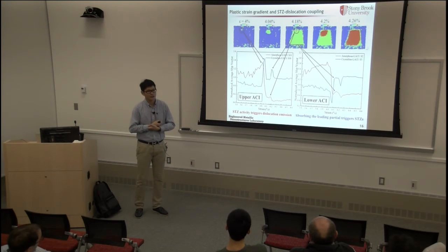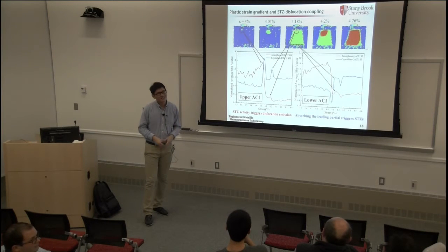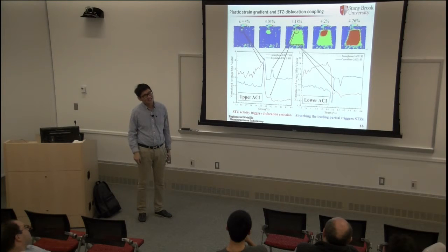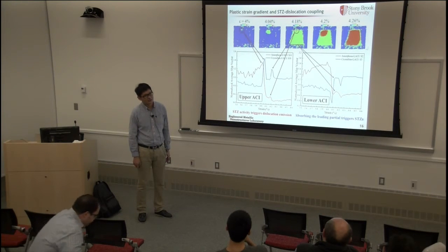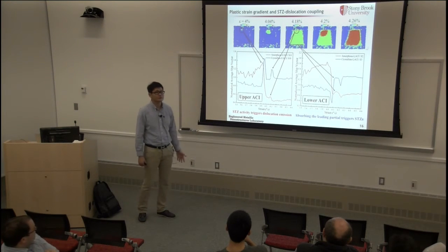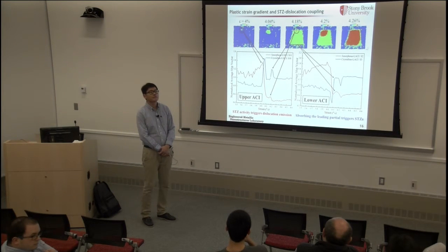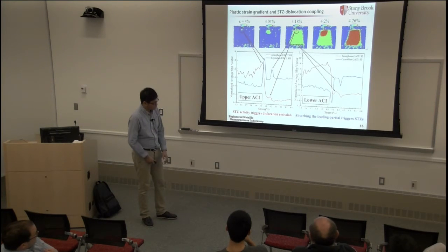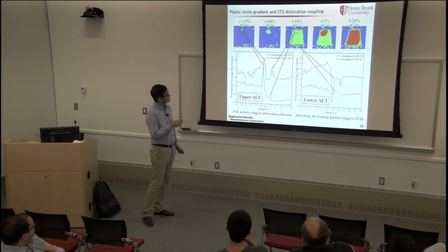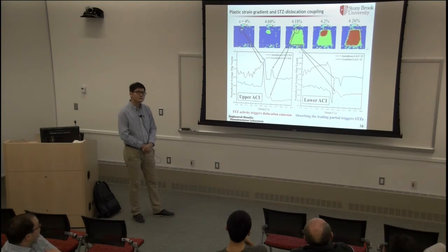Thank you. That's actually what I was hoping you would say, something along those lines. That opens up your next step. Something that I think you overlooked here, and that I'm seeing now, is that you have two different events occurring. You have one where the dislocation emits from a grain boundary and amorphous crystalline interface intersection. That suggests it has something to do with a fundamental shift in activation energy, whether it's stress concentration induced or induced by some other mechanism. When you look at the trailing partial, that little red dot, where the trailing partial is emitted does not occur at the same point. In both cases, it occurs where you have high atomic slip at that interface.